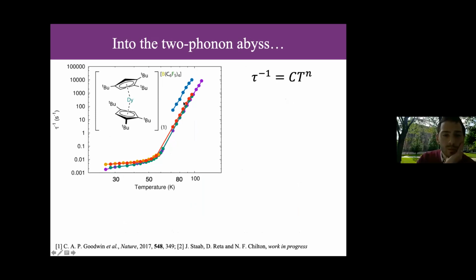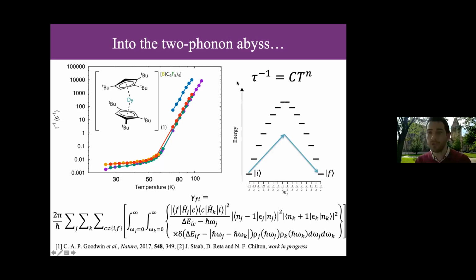So this is the original dysprosocenium cation from the Nature paper, and we found, of course, at low temperatures, this abrupt change in relaxation rate from the Orbach regime. And this is the Raman, the 2-phonon Raman term. This has a power law temperature dependence. And this is a true 2-phonon process.